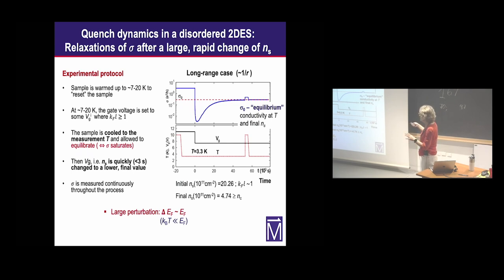Then when we see that this has almost saturated, we warm the system up to high temperature and cool it back down again at that same density, just to verify that we waited long enough. So this seems to be the equilibrium value for this average conductivity, and that's what I will call it. This is one experiment for one density, one temperature.